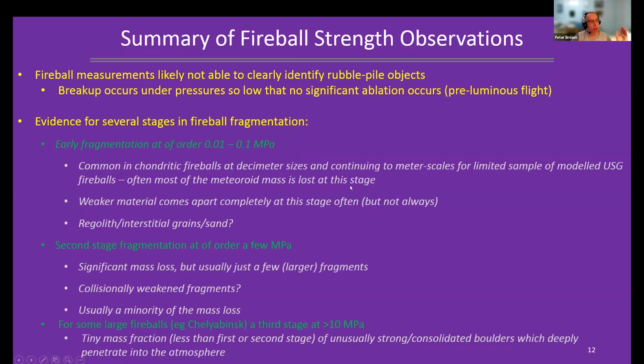What we see is we don't see a continuum in fragmentation strengths, particularly from ground-based measurements. We see a couple of distinct stages. Early fragmentation, that typically for smaller fireballs anyway is where most of the mass is released, at a few hundredths to maybe a tenth of a megapascal. Second stage of order a few megapascals. And then for some larger fireballs, we see some competent material that have dynamic pressures that are able to survive up to tens of megapascals.